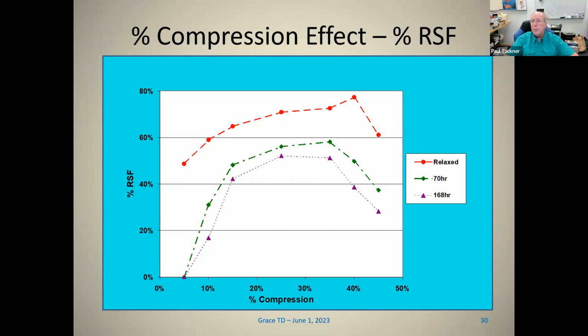In that intermediate region, you have the best retention of sealing force. And at high percent compressions, you have higher sealing force, but you lose it faster. So at some point, you end up having less sealing force than you would at an intermediate range. From that, it gives you some idea of how to optimize percent compression, and that depends on material, max temperature, and fluid exposure you're dealing with. Each of those will affect that.